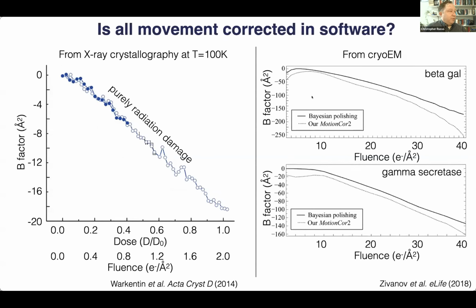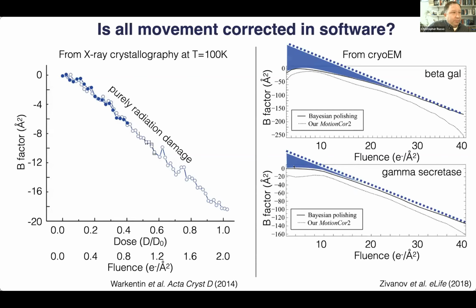And in cryo-EM, even in the best high-resolution structures from using all of the best motion correction algorithms, we still cannot get this. The first frame is always worse, or at best about the same as subsequent frames, at around 4 or 5 electrons per angstrom squared. So you always see this phenomenon where there's a maximum and then it starts to decay like you might expect from radiation damage. But what we would want to have is a linear decay starting absolutely from zero dose in order to be certain that the first frame, first of all, is the best, and that now we have no motion that is actually blurring the information in the image.